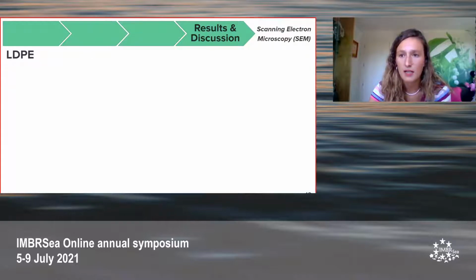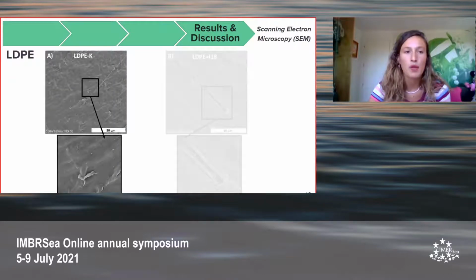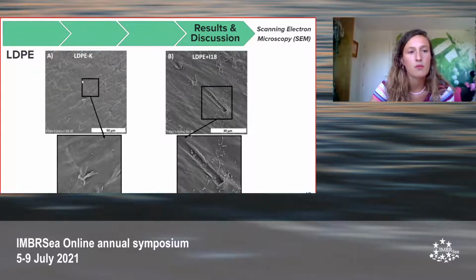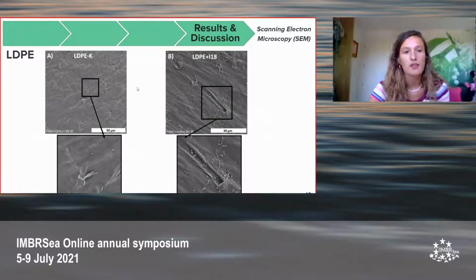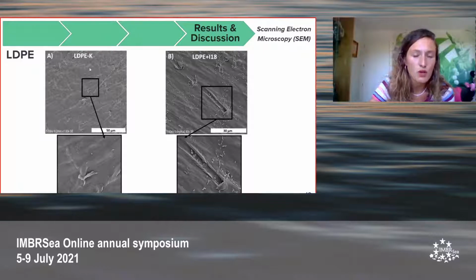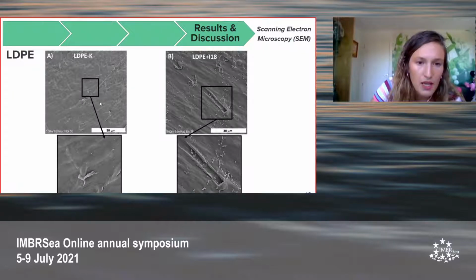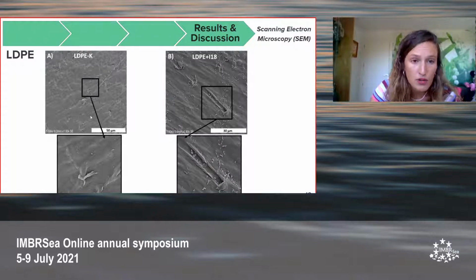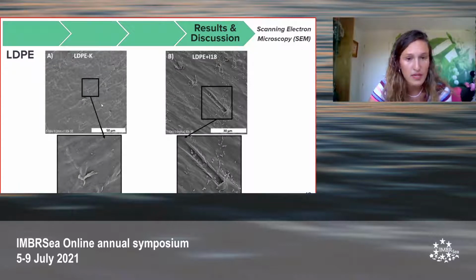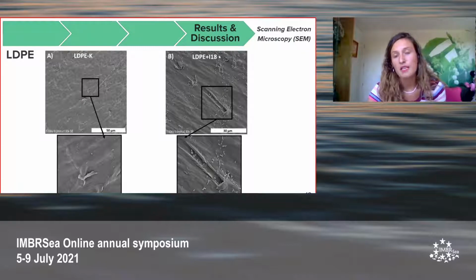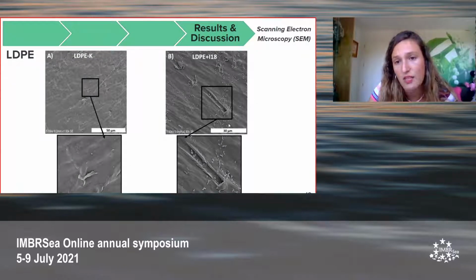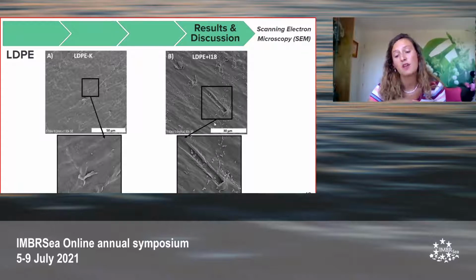In the case of the scanning electron microscopy results, again, we analyzed both polymers, and we compared the controls with the ones with inocula. The surface of the particles in the control is much smoother, and there are no signs of bacteria attached to them. Whereas in the ones with inocula, we observe some fractures and holes in the surface, and also some bacteria attached, and the formation of bacterial biofilms. These are all indicative of polymer degradation.